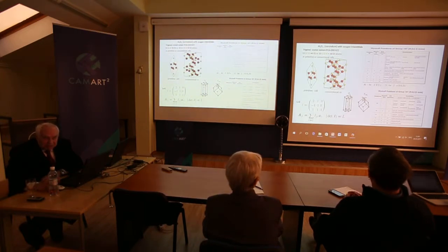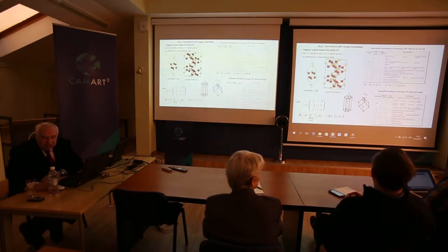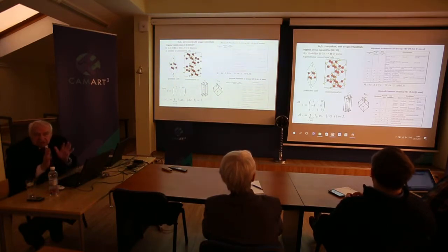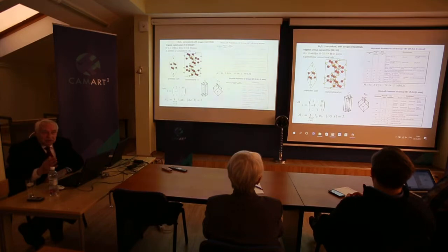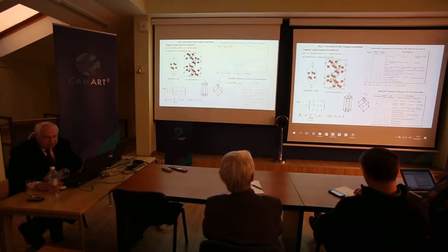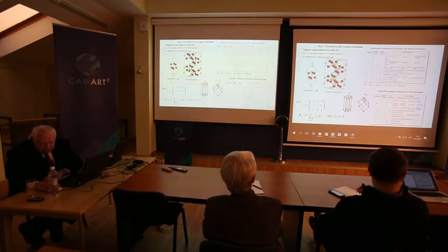Is it clear that there are 4 parameters, and a primitive unit cell consisting of 10 atoms? Non-symmorphic space group with rhombohedral lattice. But crystallographers like the hexagonal unit cell, not rhombohedral. They think hexagonal is better. Then you have again 2 parameters for the lattice, C and A. In the plane, this is C, and these are in plane. The angle is 60 or 120, but the length is equal. So the same two parameters, but the coordinates of atoms in hexagonal axes are different.